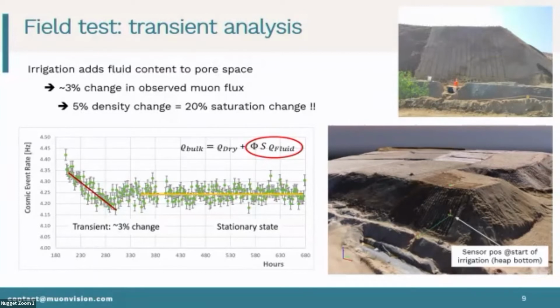It just appears that there is a discrepancy, which we think is significant, but may need to be validated or investigated further. And this potentially points to the fact that at the end of the transient phase, you might have created, from channeling, some damage to the heap such that it doesn't retain the fluid content that was designed. So this may mean that you wanted to operate with a fluid saturation of, say, 25 to 30%, and you might actually be working with something which is a little bit less.